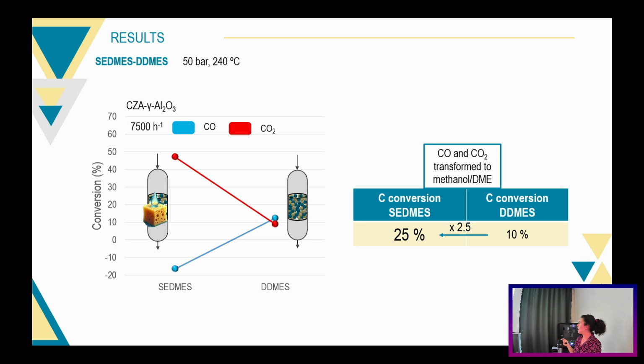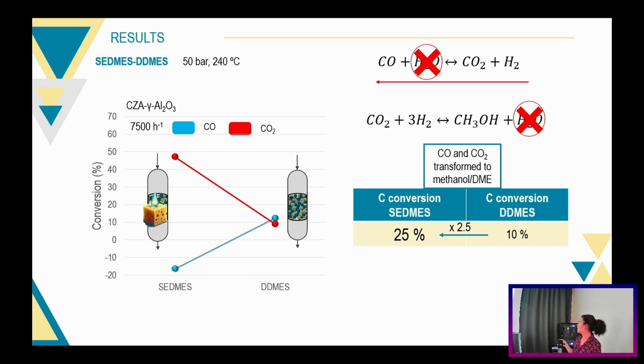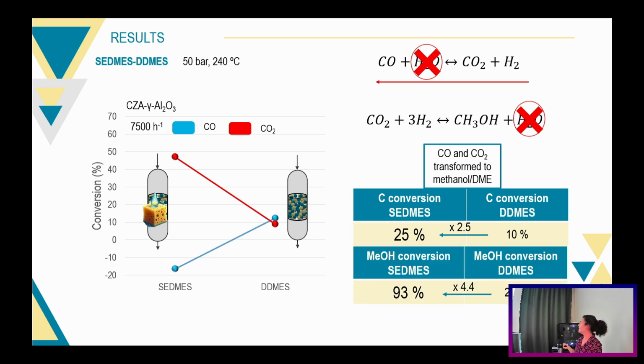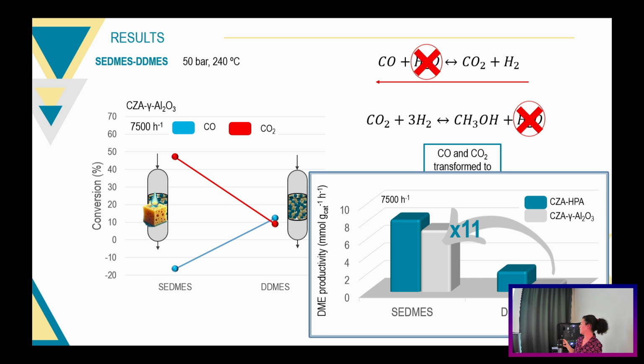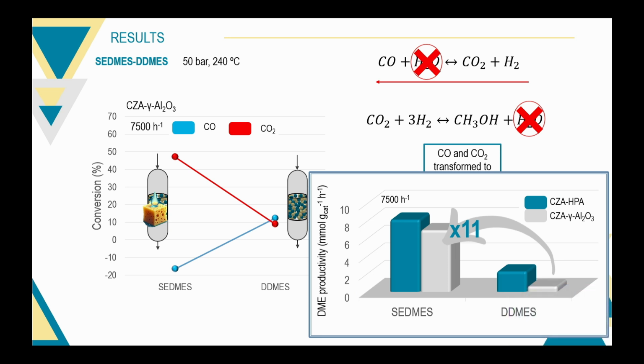We observed a net increase in this total carbon conversion, and this meant that although we were favoring the reverse water-gas shift reaction by removing water, that can be observed here with a conversion of CO2 negative, meaning that we're producing CO, we were also increasing the methanol formation rate through CO2 hydrogenation. So this enhancement in combination with this other enhancement can explain this huge increase in DME productivity for the gamma alumina containing bed.